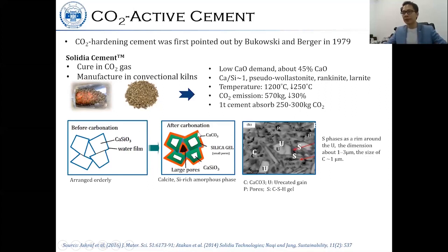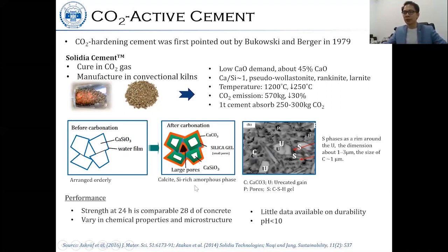And in the reaction, we can see after the carbonation, they form the calcite and silica gel to build up the pore. And the microstructure looks denser than conventional concrete. And the strength at 24 hours is comparable to the 28 days conventional concrete. And the major concern is the low pH value. It is lower than 10, so there is a potential risk for corrosion. As I know, they already work on this together with the Lafarge cement company to make this application wider and solve these different challenges.